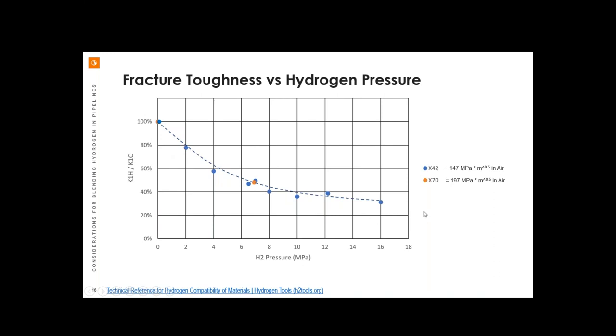There's a number of different methods used to calculate this, but we are seeing a trend with fracture toughness as it starts in air and then degrades with increasing hydrogen partial pressure. So here's a 9.9 MPa, so 10 MPa line, say, or that would be 1440 psi operating pressure. And if it was 100% hydrogen service, we could expect about a 60% drop in the fracture toughness. They do start with nice, high values though, but 60% is still a lot. And if we're talking about, say, a 10% blend, that would be about 10% loss.